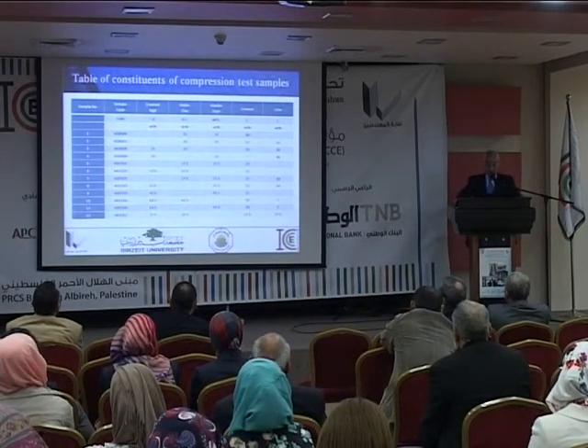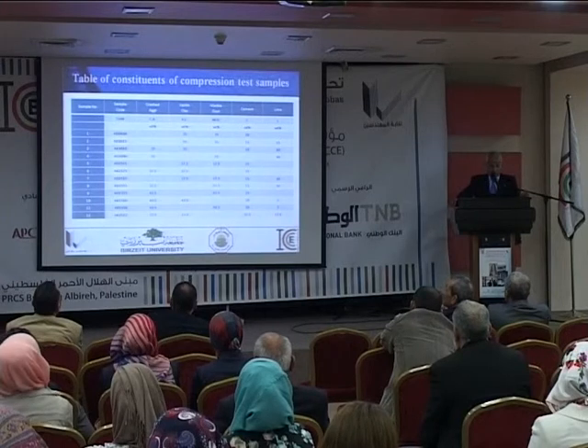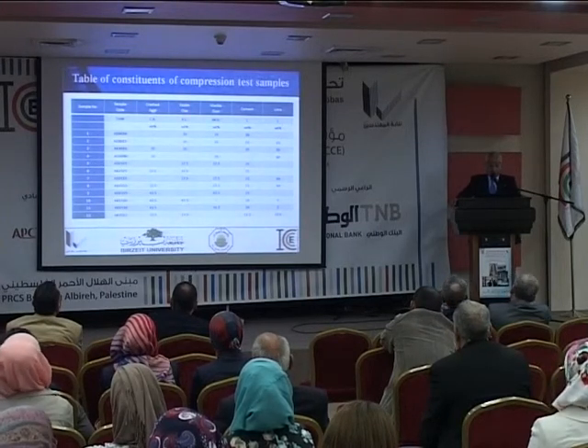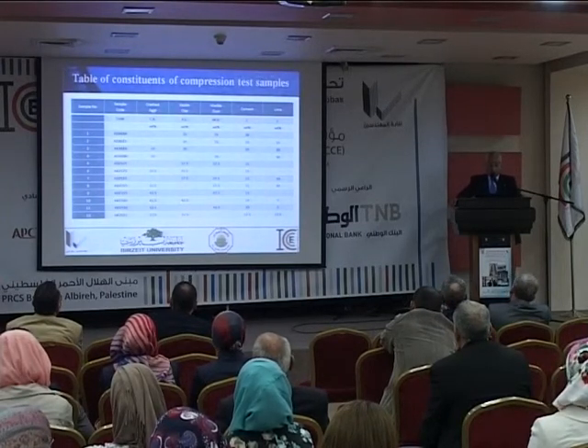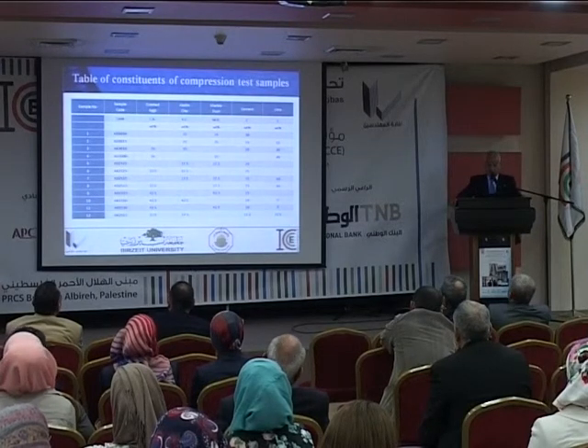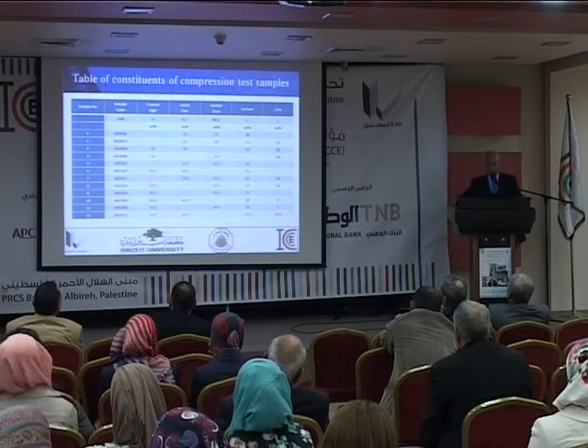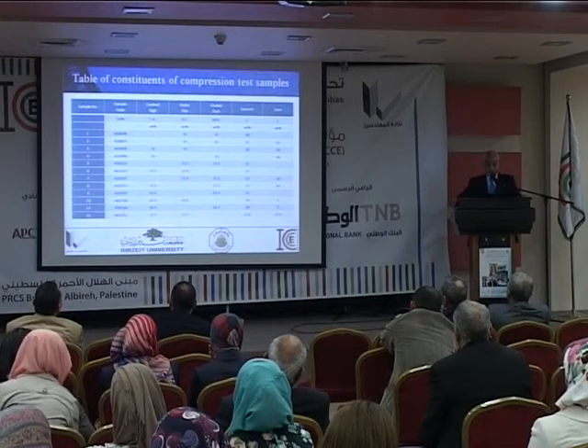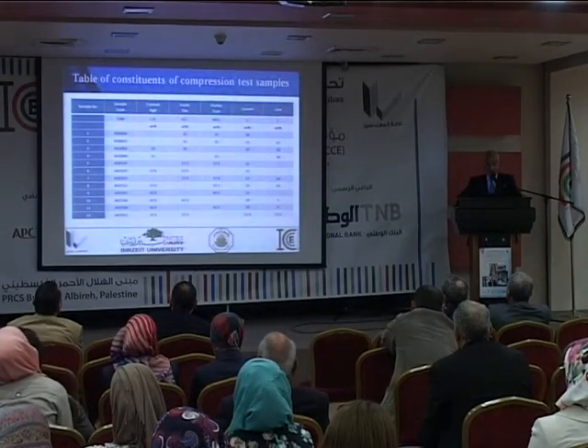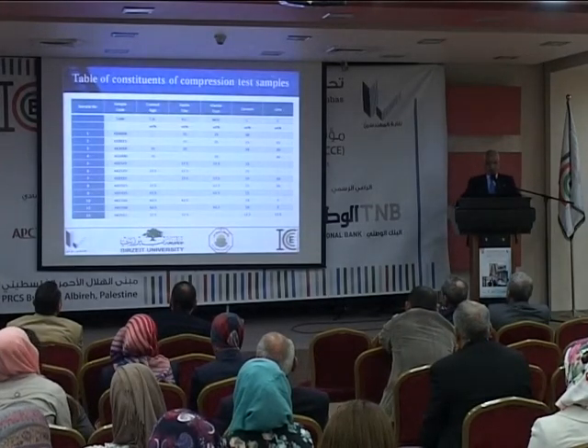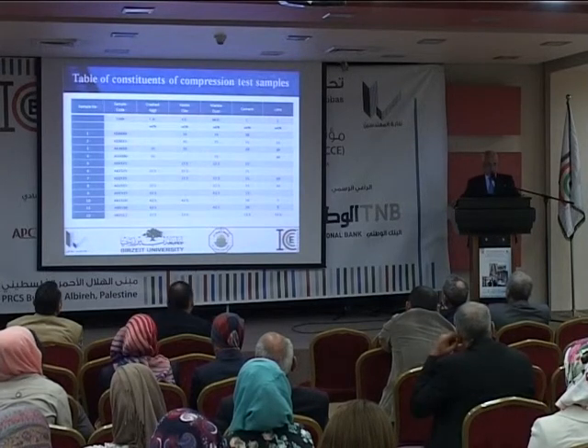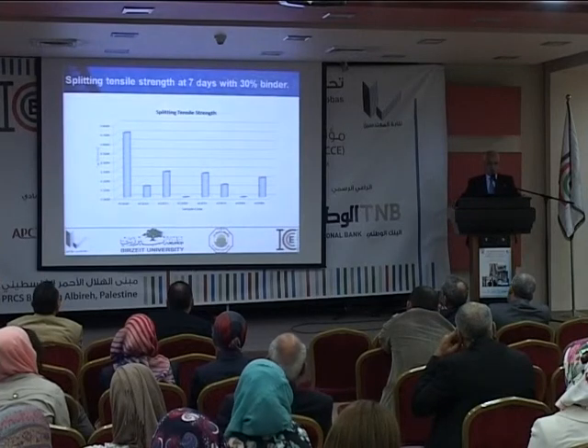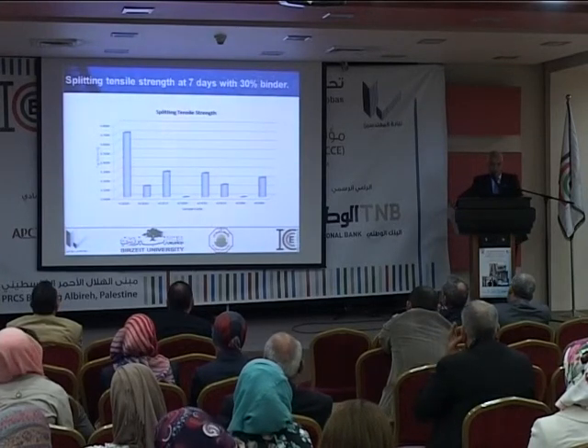Here are the main samples that we concentrated on, and they had again crushed aggregate, Kaolin clay, marble dust, cement, and lime. And we varied the percentage of cement from 30% to 10%, which is quite a huge saving if you can reduce the cement content to 10%, both environmental and in cost. You can see here that the